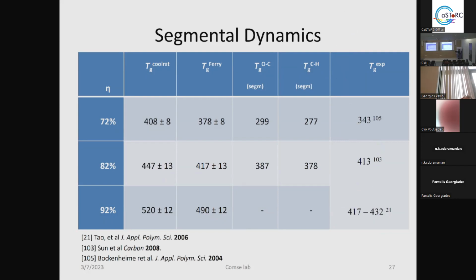Interestingly, we can see that with the brute force cooling rate method we have quite good agreement with experimental. In contrast, the WLF method, although it has some qualitatively good results, quantitatively has some variance from the experimental values, and the reason is the sensitivity again of the method. The more sensitive the method is, the bigger the error transferred to the final values, especially if you have small systems like we had.